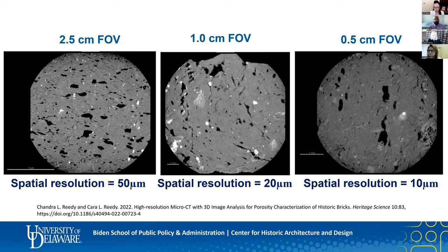So in my first two exploratory studies, I imaged all samples at both fields of view and then repeated the same image analyses for both sets of data. Then my data scientist, Cara Reedy, did the same statistical analyses for both. It was a lot of tedious additional work, but it was useful because the statistical analyses for both projects clearly showed that the finer spatial resolution gives better results. More pore variables were useful in answering the research questions.